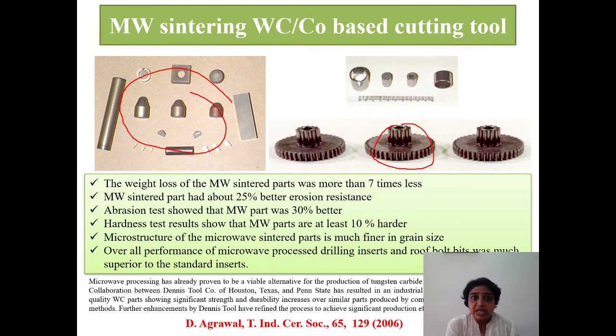What were the findings? The weight loss of the microwave sintered parts was more than 7 times less, because this is very fast, so evaporation of the material is less. In zinc oxide also, if we go by the conventional method, zinc gets evaporated, and that leads to a non-stoichiometric compound. So here is stoichiometry. This is again a very important feature of the microwave, that stoichiometry of the compound can be maintained. The microwave sintered part had about 25% better erosion resistance as compared to conventionally sintered cutting tools. The third one is that they were better performers in the abrasion test, and the hardness test revealed that they are 10% harder than the conventionally sintered parts.